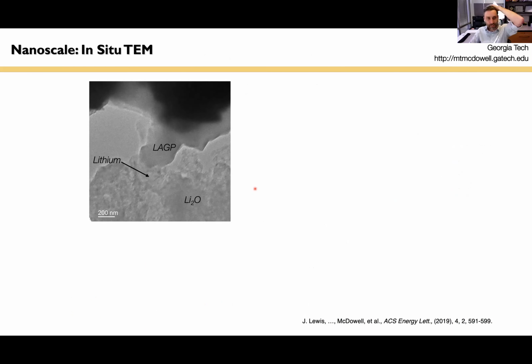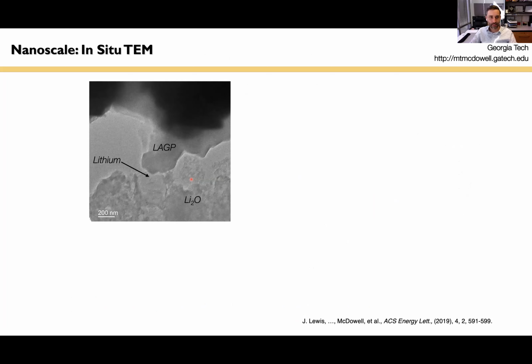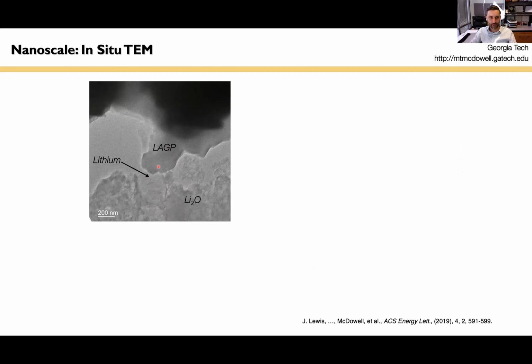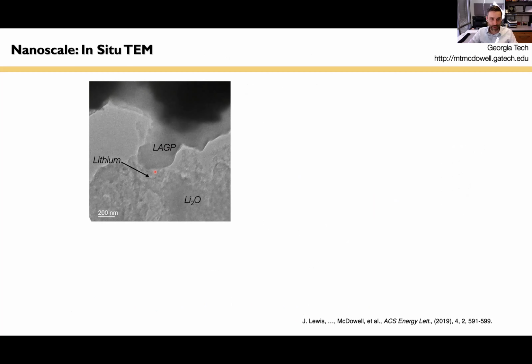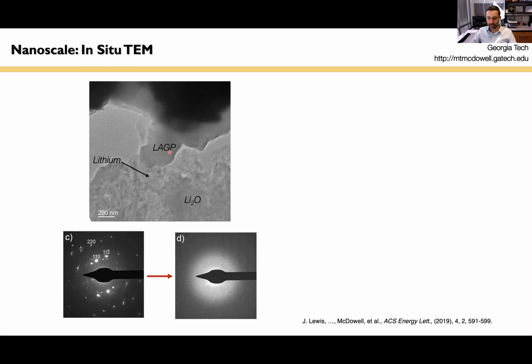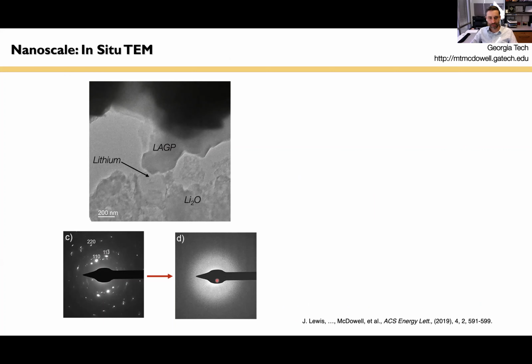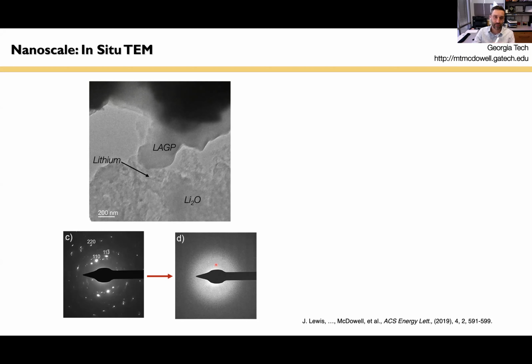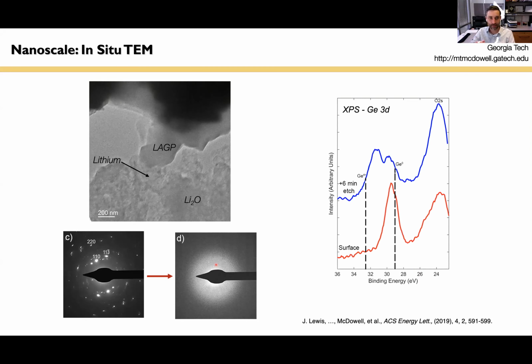One of the things that we did was in situ TEM. I won't dwell on this right now because I'm going to show a little bit more data in about 10 minutes on this. But these are some experiments we do in my group where we basically bring a material of interest in contact with lithium. We do that here with this solid electrolyte material. Here's a little crystal of a solid electrolyte, this LAGP material. We're bringing it in contact with lithium inside a TEM at fairly high magnification. And you can see here that there's an expansion process, there's a reaction process. What we're doing here is amorphizing the initially crystalline solid electrolyte to form an amorphous phase. So this is a big structural change when we react with lithium. The interphase process involves reduction, and in this particular material, it involves amorphization. So this already gives you a hint that we're probably not forming these thermodynamically stable compounds.